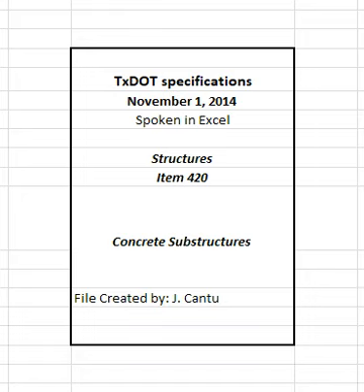Revise the heat control plan as necessary to maintain the temperature limitations shown above. If the core temperature exceeds 160 degrees Fahrenheit, the mass concrete element will be subject to review and acceptance by the engineer using forensic analyses to determine its potential reduction in service life or performance. Proceed with subsequent construction on the affected element only when notified regarding acceptance. Repair any resulting cracking if the temperature differential between the central core of the placement and the nearest concrete surface exceeds 35 degrees Fahrenheit at no expense to the department, and revise the heat control plan as necessary to prevent further occurrences.